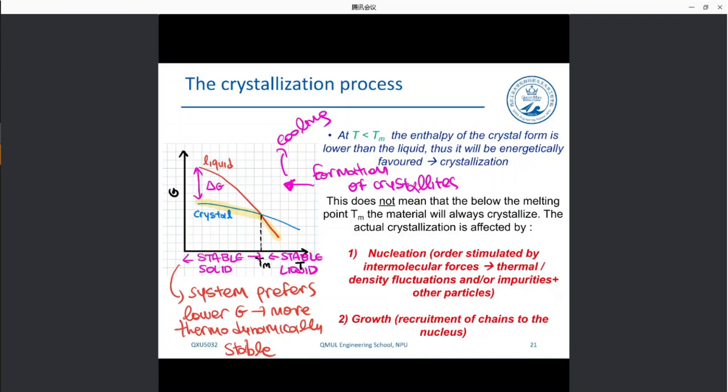I'm pretty sure you've seen this experiment where you put a bottle of water in the freezer, and when you take it out, it's still liquid, but when you cool it down very fast, that causes a density fluctuation, and then it crystallizes immediately. That is what a density fluctuation is. And also, in order to induce nucleation, we use some particles or sometimes some impurities that are present within our polymer, where nucleation takes place at these sites. This can be additives such as fillers or pigments. Impurities can be, I don't know, dust that is present within a reaction vessel and so on.